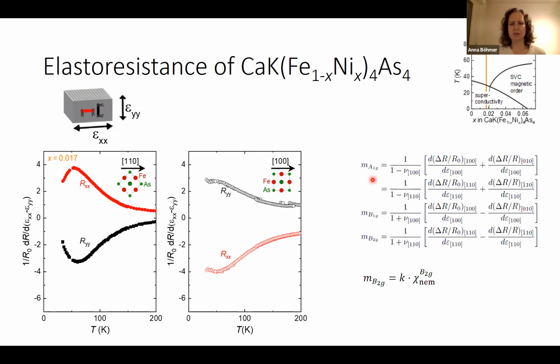And to obtain the symmetry components of the elastoresistance tensor, the sum, the A1g component, that's basically the sum of the two. And we see because of the sign change that will largely cancel out. While the B1g and B2g components, that's the difference of the two, that's the ones we are going to look at. And again, that was just mentioned in the previous talk, the B2g elastoresistance coefficient is proportional to the B2g nematic susceptibility. That's the one that's related to our stripe order.